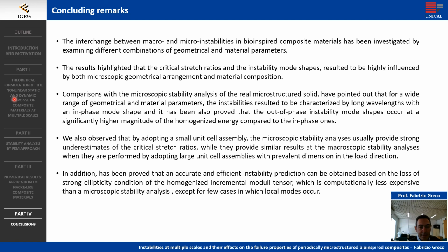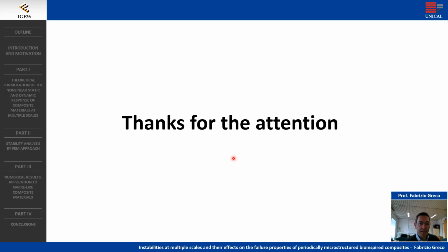Finally, we can observe that stability analysis can be based on the criterion of the loss of strong ellipticity condition referred to the homogenized incremental moduli tensor, which is less computationally expensive than a full-scale microscopic stability analysis, which must be carried out by using a finite element approach. And only a few microstructural morphologies, characterized in particular by low values of platelet volume fraction and shear modulus contrast, together with high values of the platelet aspect ratio, require a full microscopic analysis. Thanks for the attention.